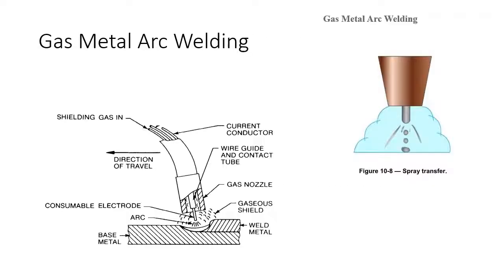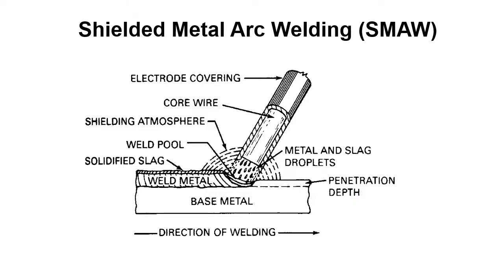A crash course on the four processes. Gas metal arc welding uses a solid metal wire, an inert gas, and a constant voltage power supply — generally anything above about 21 volts. Short-circuiting mode of transfer is prohibited for pre-qualification. Shielded metal arc welding — this one is pre-approved. You've got a covered electrode with a core wire. It's the most widely used welding process on the planet, a good solid portable process used the world over, and you can use it as pre-qualified.